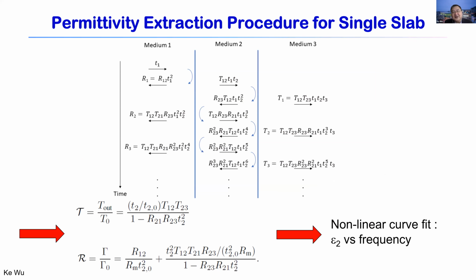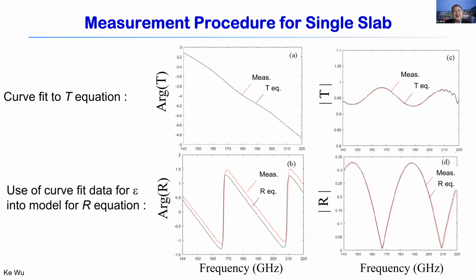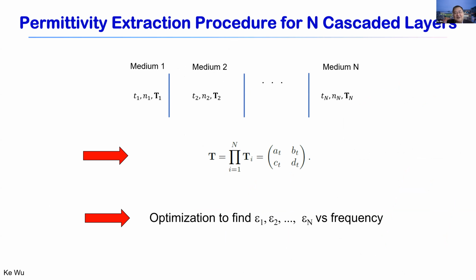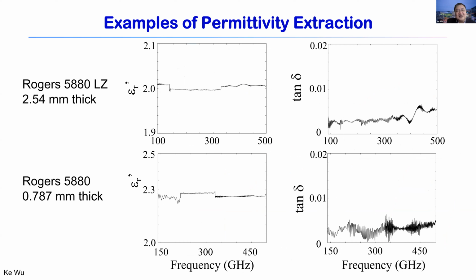We also developed single slab multi-reflection models for the same technique. Based on those multi-reflection models, we developed transmission and reflection equations. These equations are analytical, which allows us to extract the real part and imaginary part of the values. I will not show you these equations here, but I will show you the measurement results. You can see the real part and the imaginary part in terms of loss tangent. The value is pretty good. There is some uncertainty over a certain frequency range, but it is still acceptable for our measurements.